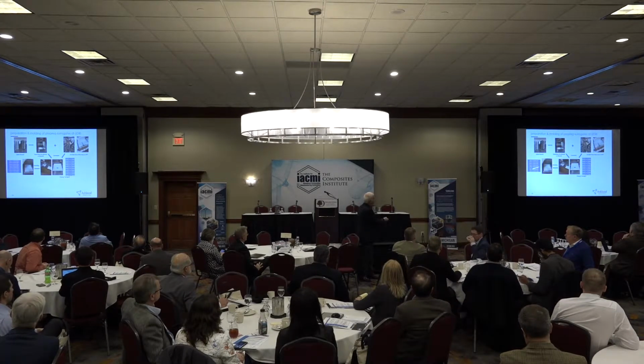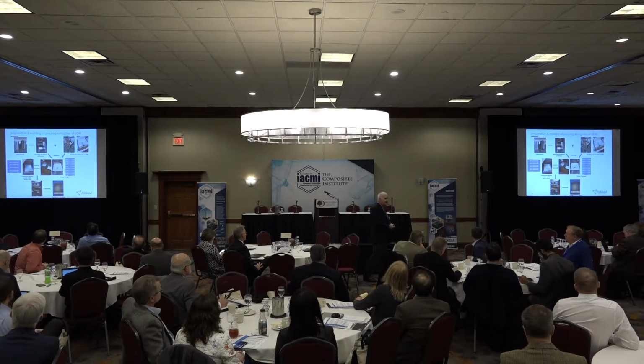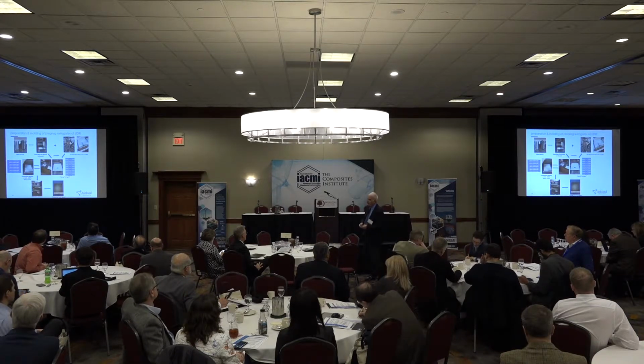To get from here to here, UDRI would do a debulking step in a heated vacuum oven. Then they would get something closer to this cartoon, which they would then compression mold, typically at 325 to 350 F, and they would produce 12-inch square plaques for thermomechanical testing that would be shipped off to Dublin.